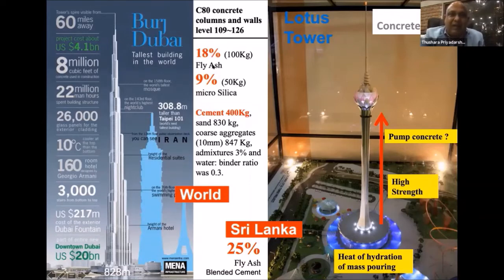So you can see, this particular mix design is used for the column C80 concrete for level 109 to 126. They have used fly ash 18%, microsilica 9%. So 18 plus 9 means 27%. So as I mentioned, at least 20 to 25% of these materials is required for you to have a durable structure. But why they have used fly ash for these columns is because pumpability really matters.